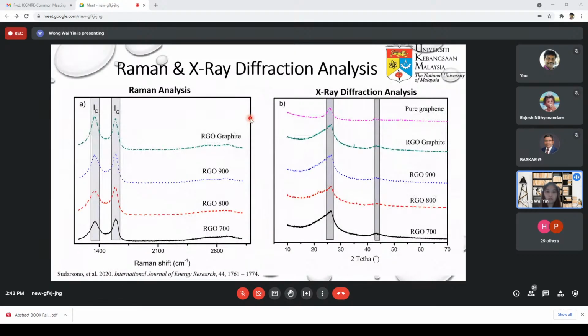Okay. To further confirm the successful formation of the RGO from the biomass, we performed the Raman and X-ray diffraction analysis. As can be seen from this Raman analysis, the peaks are similar to the RGO from graphite, but with temperature increase, you can see that the ID to IG peak increases, indicating that the defective intensity in the RGO 900 is higher than 800 and than 700, simply because at 900 degrees Celsius, at high temperature, more volatiles have been removed, and that leaves the defective sites on the surface.